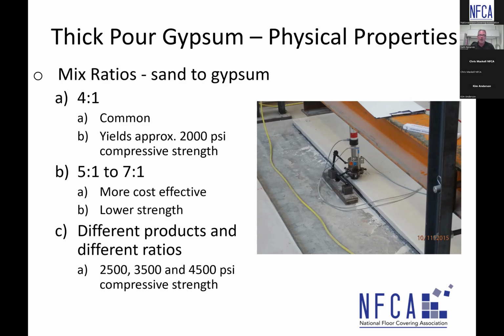But the thing I want to point out, even though generally speaking a 4-to-1 yields a 2,000 psi compressive strength, there are different products that the manufacturers have out there in different ratios that can achieve a 2,500, a 3,500, a 4,500 psi compressive strength gypsum. So while in the past the 4-to-1 was very common and the typical gyp that you see out there, and it still may be so present day, there are other products that can be used on site as well that arrive at higher compressive strengths due to their mix design and ratios. So I just wanted to point that out.